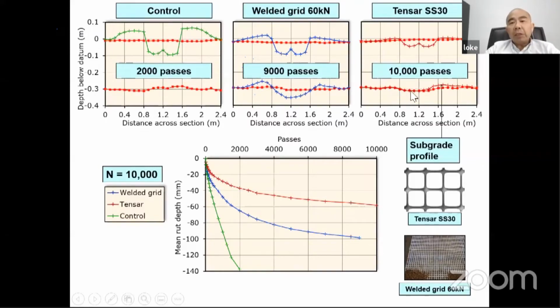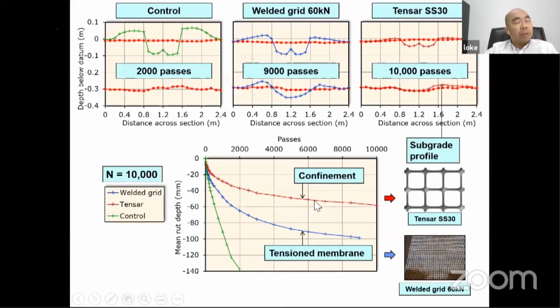But if you're using a stiff geogrid, you can see very little deformation at the subgrade. So as you know, this is 300 millimeters, and you can see very small deformations at the surface of the road. Okay, so you can see here, this is what we call a tension membrane. It settles a lot, and this is what we call a stabilization or a confinement function. You can see here, as you read across the graph, it can tolerate about 6 times or 8 times better than a flexible geogrid.